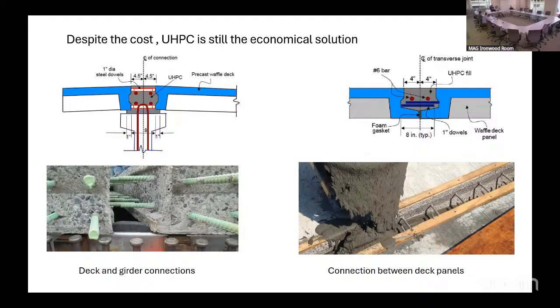But I can verify that every single ready mix producer can make this in the Valley. With the cost of one bridge replacement, they have now rehabilitated more than 7 bridges, extended the life. And the reports are available. Jimmy Camp, who's the head structural engineer, is totally bought into it. The idea is that if you're replacing a bridge, you can order precast girders, and when you put them in there, for the connection pour, you use this ultra high performance concrete, which has a tensile strength of about 2,000 PSI and compressive strength of 20,000 PSI, which means that this thing is not going anywhere. This is going to glue everything together.